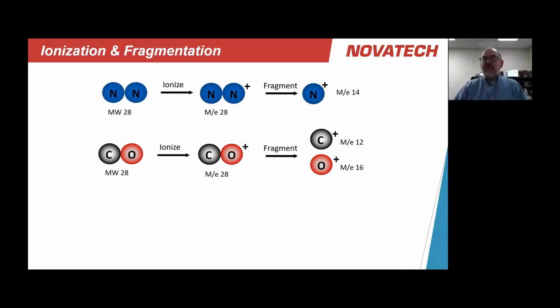But one of the things that happens within that ion field is we also create fragments. And the fragmentation pattern of these molecules is well known and understood. We know where the fragments for nitrogen are. We have a big peak at 28, but we have another peak at 14. Similarly for carbon monoxide, big peak at 28, two other peaks at 12 and 16. And because we know the fragmentation patterns and we know the relative strengths of the fragments to the main peak, we can use math to separate out what each individual component is.